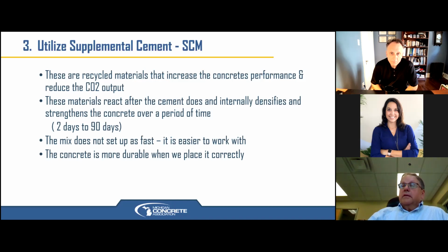And the 28-day strengths were always what we needed for stripping and opening to traffic. In many cases, we're getting open-to-traffic strength in Michigan with our paving mixes in less than 24 hours. But this densification, this waterproofing of our concrete is something that the supplemental cements do for us, and that happens over a longer period of time.